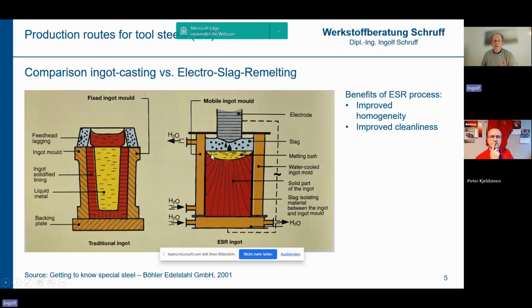So under the slag, we have a melting pool in which we have a small volume of liquid purified steel. Then this whole process occurs in a mold, which is usually made of copper with installed water cooling. So we have a very fast or comparably fast solidification in the radial and also the axial direction. The solidification is much faster than in this traditional ingot casting if we compare similar cross sections.